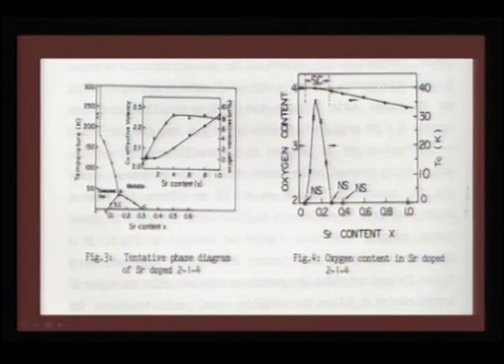Coming to the phase diagram, we can understand how critical the doping concentration is. As I told you, La 2 minus x Sr x CuO4 has a critical concentration of strontium. If you make a substitution of strontium in the lanthanum site, then you can look at the Tc maxima, and you would find the Tc is maximum only for a critical composition of say 0.15. Beyond that, if we keep doping, then the superconductivity tails down. So, this is the region where you can aim at strontium doping. Strontium with x of 0.15 is the compound which will give you maximum superconductivity, beyond which you would see it is in a metallic range.